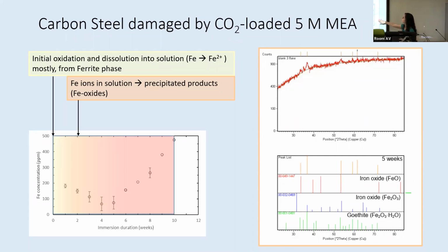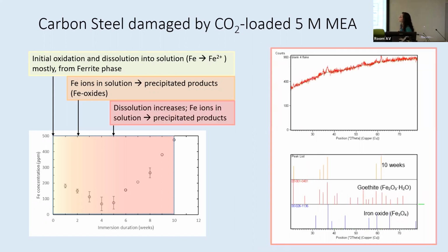And you can see that we have a little bit of a shift in terms of a broader spectrum of types of iron oxide. Now, as we continue, what we see is that uptick back up again of the concentration, reaching some high levels, which we would expect would continue. A few notes about that are really important: that could be coming from two sources. It could be continued oxidation from the surface of the iron of the sample, or it could be that there's reprecipitation of some of those products.